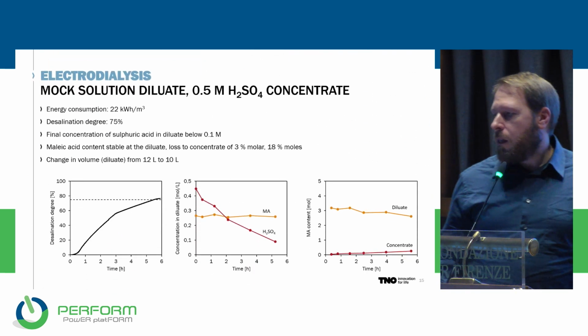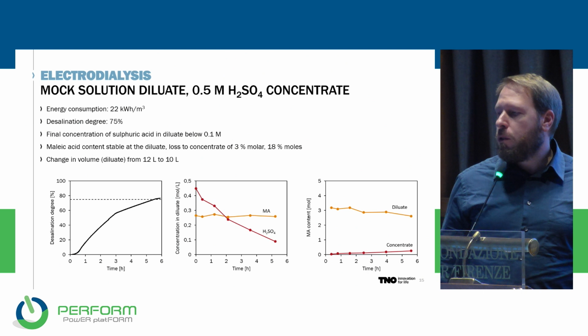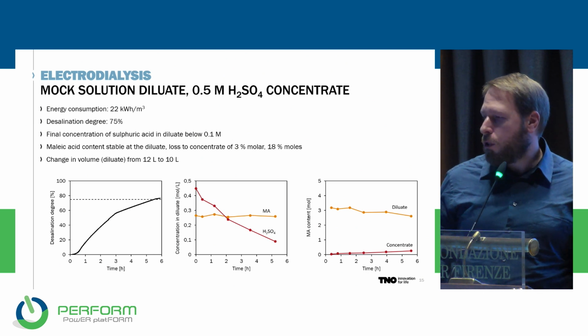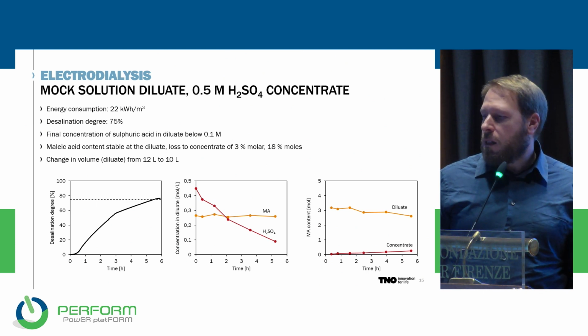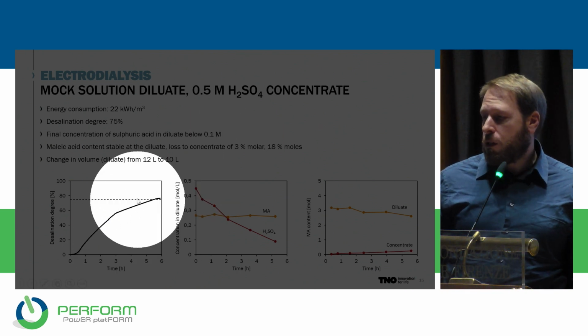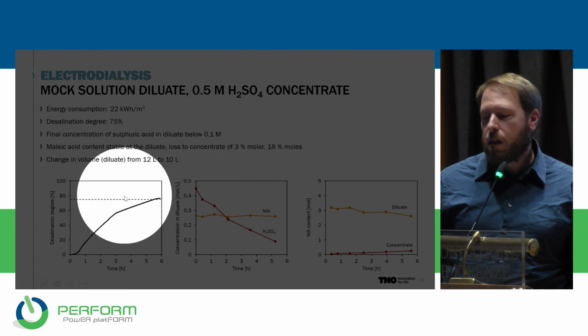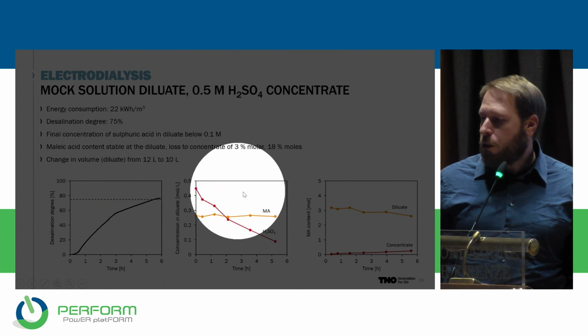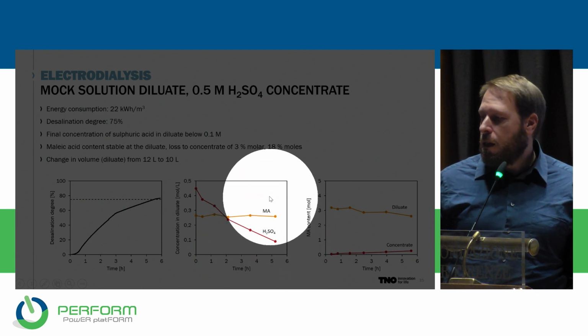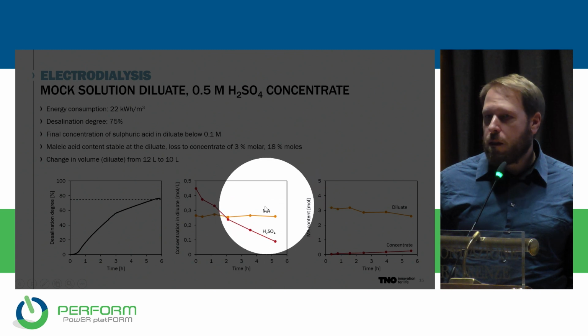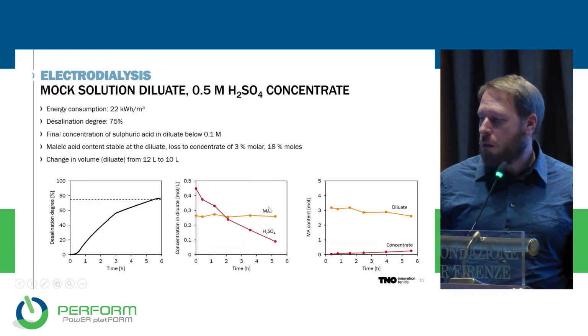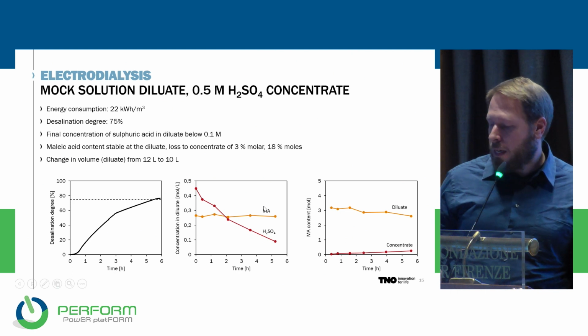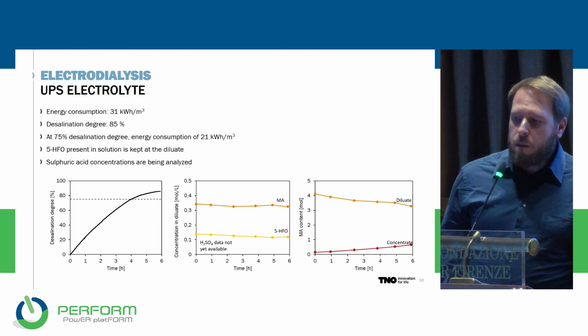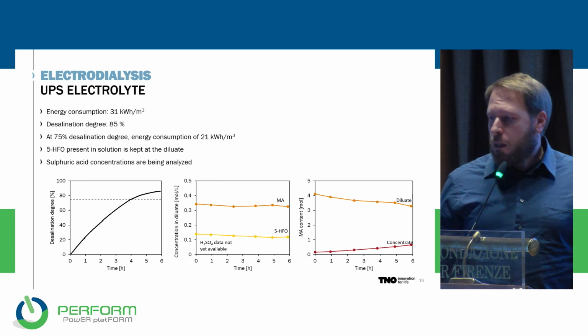We have actually run this process on a mock solution just as a showcase, and we can see that we can reach a desalination degree of around 80%, and within this desalination, we remove most of the sulfuric acid, but we keep all the maleic acid in solution, so we lose a very small amount of maleic acid.